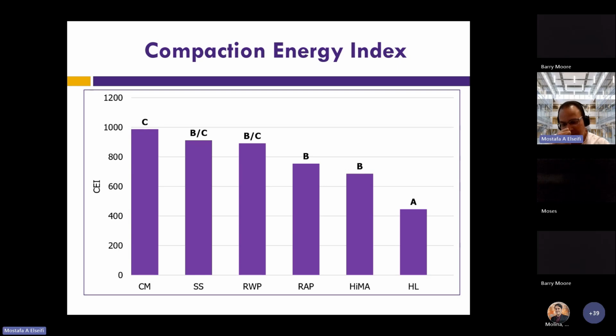The compaction energy index showed us very interesting results. The control mixture had the highest compaction requirement, which is shown here on the left, so it had this C grouping. In contrast, the hydrated lime, followed by the HiMA and the RAP, had the lowest compaction energy requirement. Why is this the case? This relates to the viscosity of the binder. And you can see that it's possible that hydrated lime facilitates the compaction process, and that's why it had the lowest compaction energy requirement.